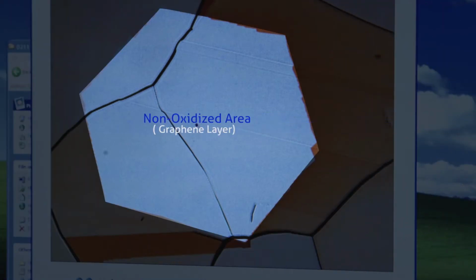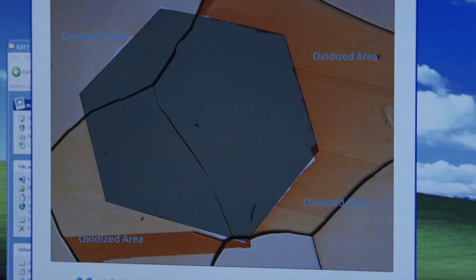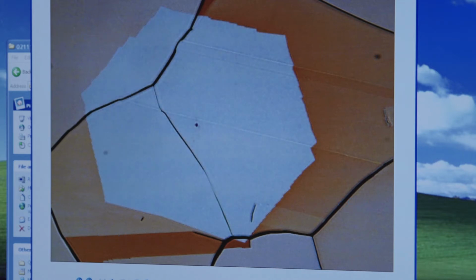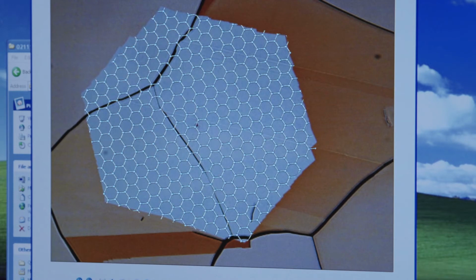It's one single crystal of graphene on an oxidized copper surface. So the white area, what you're actually seeing is in the white area, it's not oxidized. The copper isn't oxidized because it's protected by the graphene crystal. And everywhere else, it's sort of orangish, which is, as copper starts to oxidize, it turns to that color. So that's why we can see a single atomic layer of carbon in an optical microscope, because we're not actually seeing the carbon, but we're seeing how, by being there, it's protecting the copper from being oxidized. And this is several millimeters across, and it's a single crystal. So it's 1 atom layer thick and a couple millimeters wide.